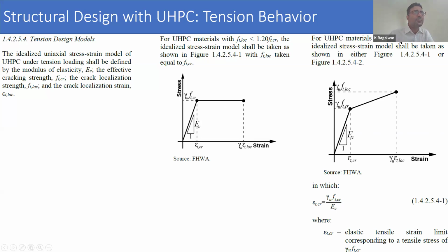And then for another one where we see very strong strain hardening behavior, if the stress at which localization occurs is higher than or equivalent to 1.2 times the first cracking strength, then this is the model we use. So we apply factors of safety to cracking strength as well as localization stress, and then the strains are equivalent to the cracking strength, which is given by modulus of elasticity, and then we also have localization strain. So these are two different blocks.